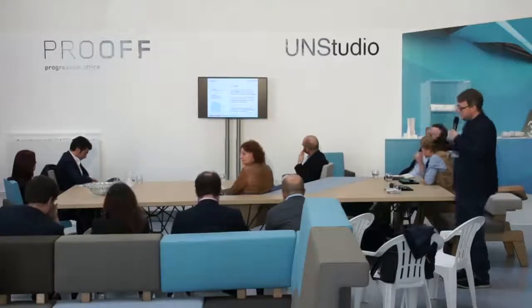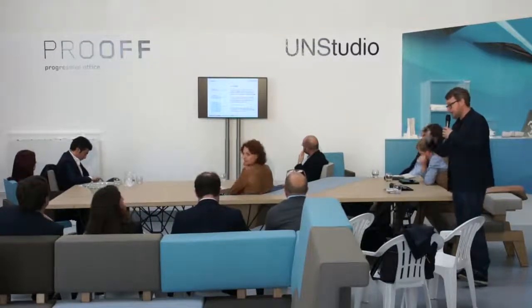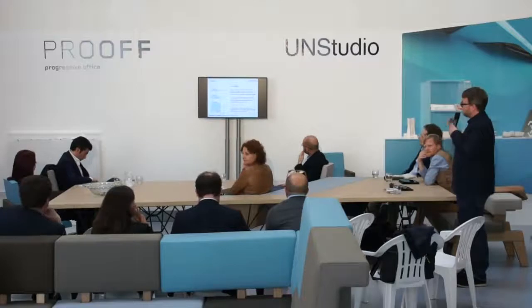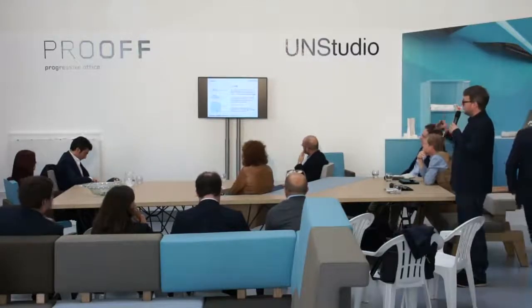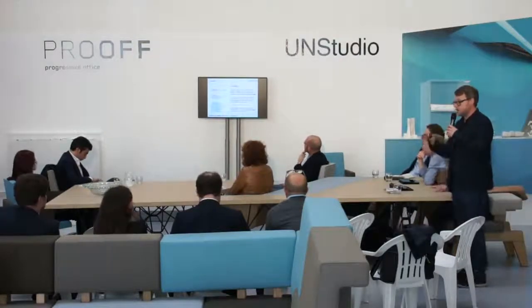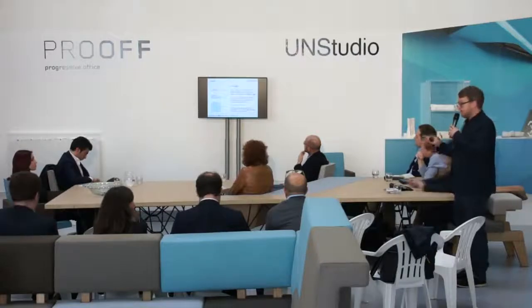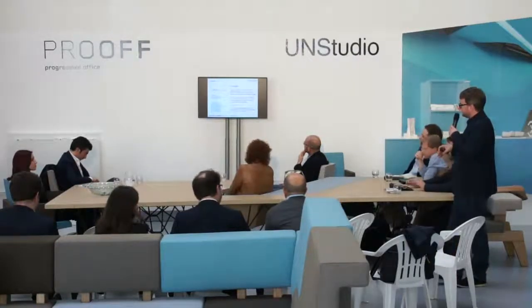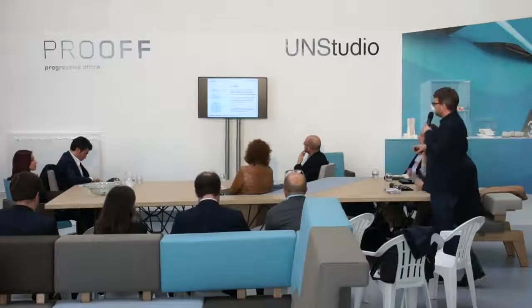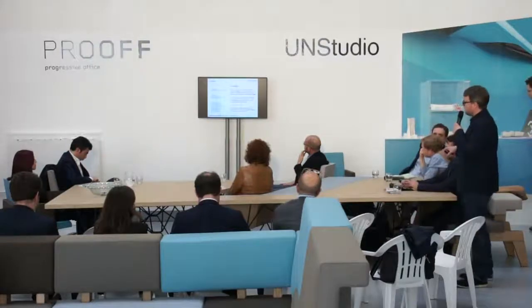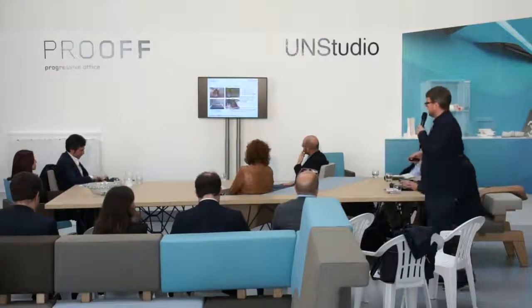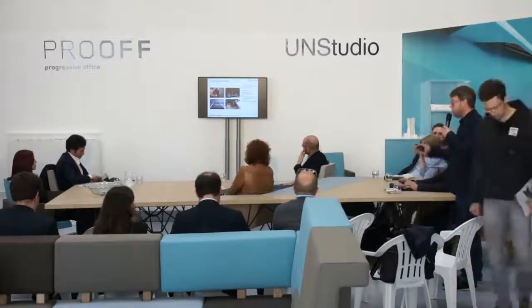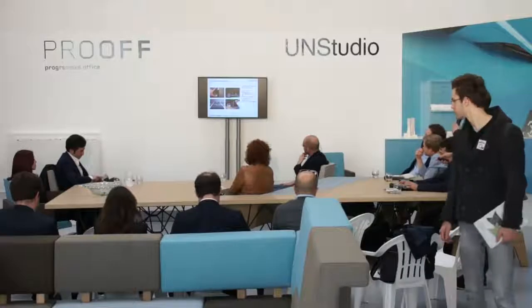So you end up with a very thin, super thin, 1 millimeter and less, very high strength, 300 megapascals piece of glass. So a 1 millimeter piece of Gorilla Glass, like your screen on your iPad or your iPhone, has a strength that is many multiples greater than that of regular glass, and in fact many multiples greater than that of steel. So here we have very thin, very strong glass, very durable. What do we do with it?